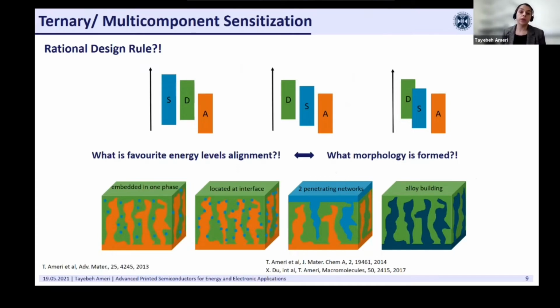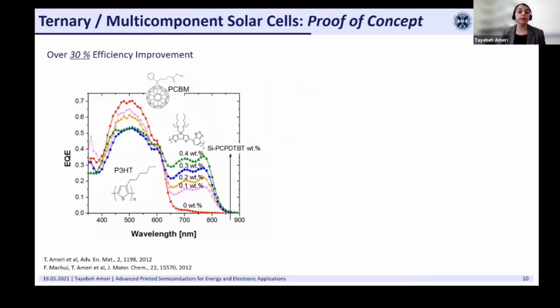But before answering these fundamental questions, it was our job to prove and demonstrate the potential of this concept. Does it make sense to put effort and time into optimizing such a concept? Here you can see that when we started our work by introducing the low bandgap polymer called silicon PCPD-TBT as a sensitizer to the host system of P3HT:PCBM, how beautifully we can sensitize and extend the absorption to the near IR regime, where our host system, the red curve, is not absorbing at all, by increasing the sensitizer content. And altogether, we were able to improve the device performance over 30%, which was great news for our technology and our community, because we did nothing except adding a bit of the third material to the system, and it's getting 30% more efficient.